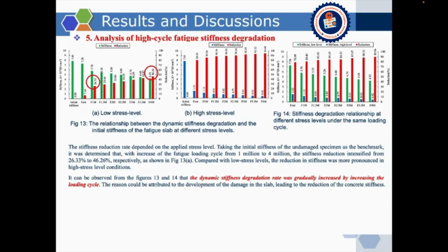Analysis of high-cyclic fatigue stiffness degradation. As shown in figure 13, we compare the stiffness of arch slabs subject to low and high stress levels from 1 million to 4 million cycles, as well as compare the stiffness degradation between low and high stress at the same cycles. In figure 14, the stiffness reduction rate depends on the applied stress level. Compared with low stress level, the reduction in stiffness was more pronounced in high stress level conditions.